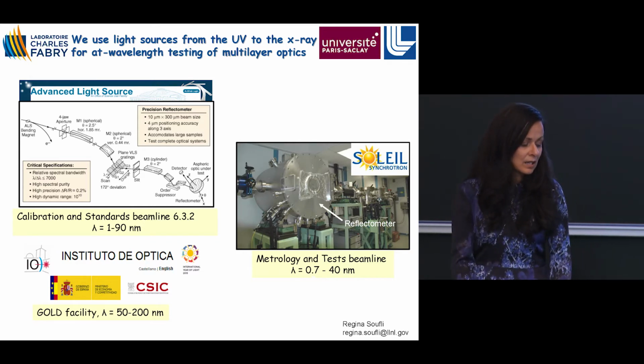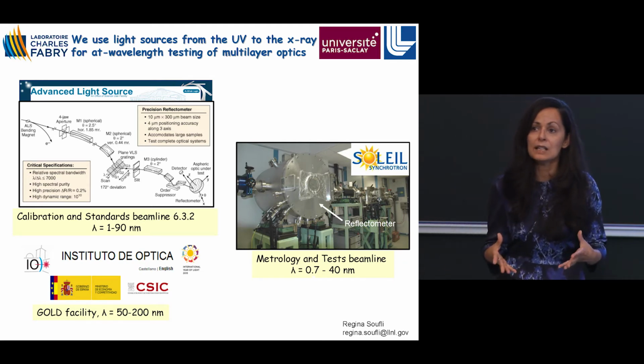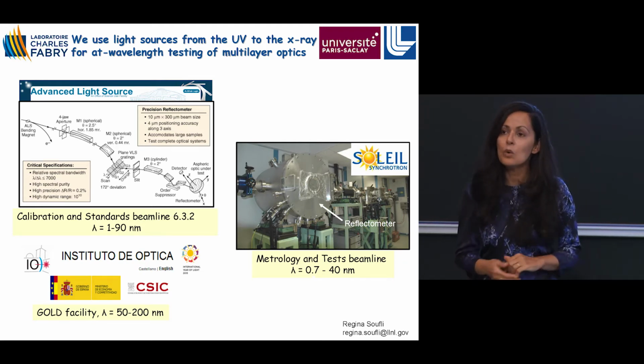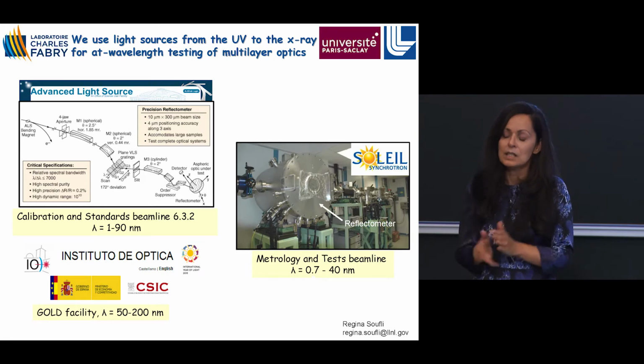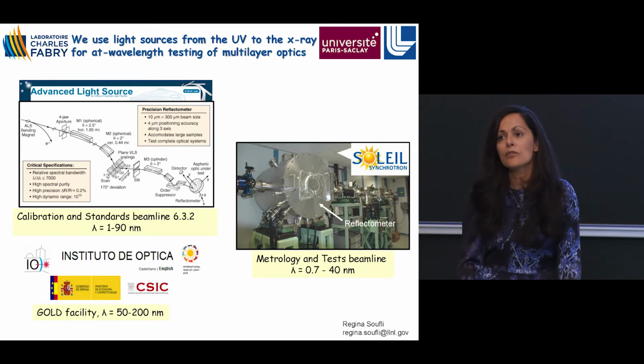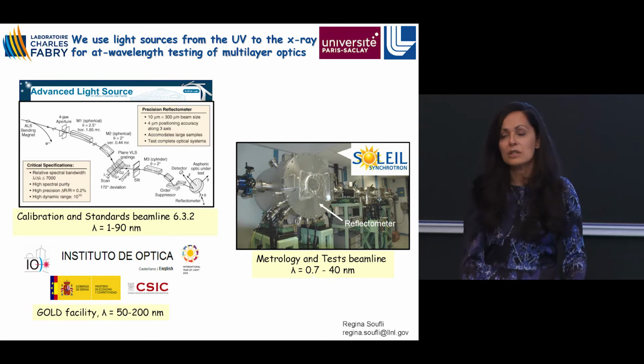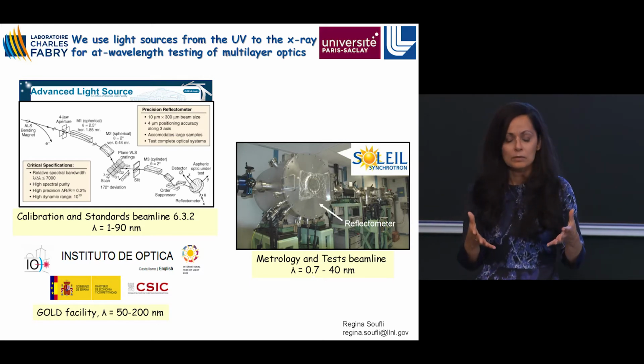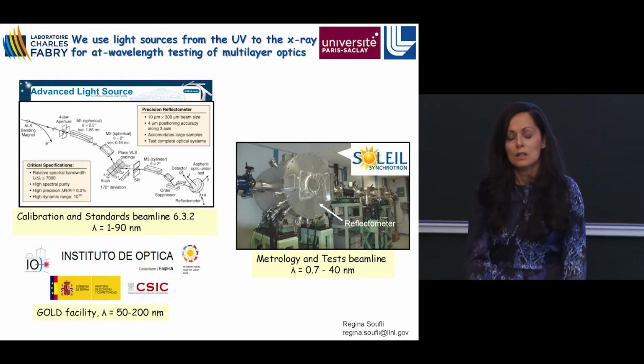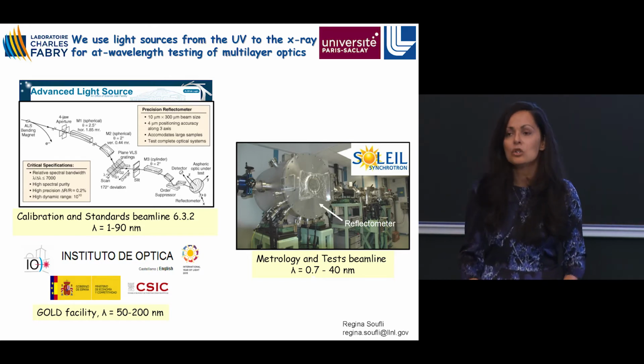But you can see that the methodology is very, very complicated. And as I was explaining for chromium, even 1% of spectral contamination in a photon energy region that is important for the measurements can completely throw off your measurement. So even with those advanced facilities, there is still a very heavy burden on the measurement and the post-measurement analysis. So they're not easy measurements to make. However, again, I will say that synchrotron sources enable this measurement. It is synchrotrons that are needed to do this type of measurement.